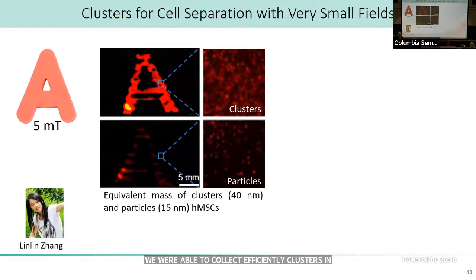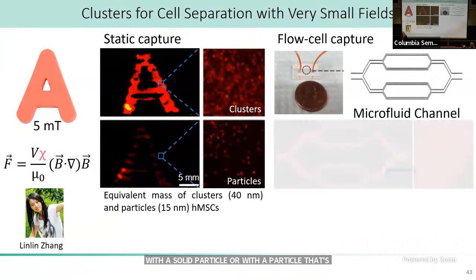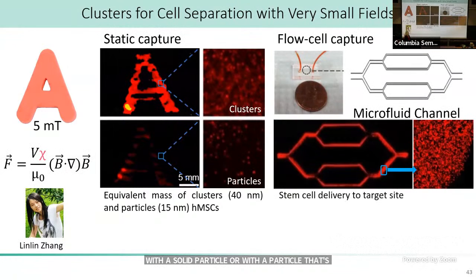Where you just can't do that with a solid particle or with a particle that's a little smaller. So these porous materials have that going for them. They're very, very easy to capture. The forces that act on these materials scale with the susceptibility. So those peaked susceptibilities mean you can pull them out of solution easier. There is a volume dependence here, so you give up a little bit there, but overall the susceptibility wins. So we're able, with extremely small field strengths, to manipulate them, at least in these examples.